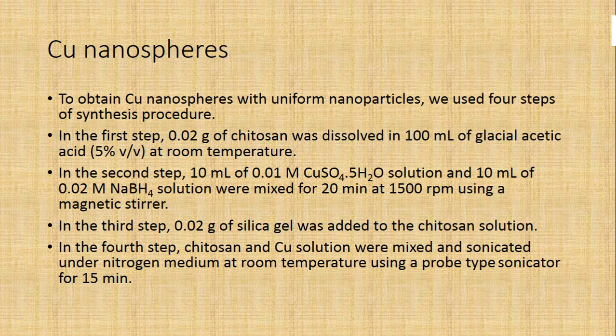Four synthetic steps were used for fabricating copper nanospheres. 20 milligrams of chitosan was dissolved in 100 milliliters of glacial acetic acid at room temperature. 10 milliliters of 10 millimolar copper 2 solution and 10 milliliters of 20 millimolar borohydride solution were mixed for 20 minutes at 1500 rpm. 20 milligrams of silica gel was introduced into the chitosan solution. Chitosan solution and the reduced copper solution were mixed and sonicated under nitrogen atmosphere at room temperature using a probe type sonicator for 15 minutes.